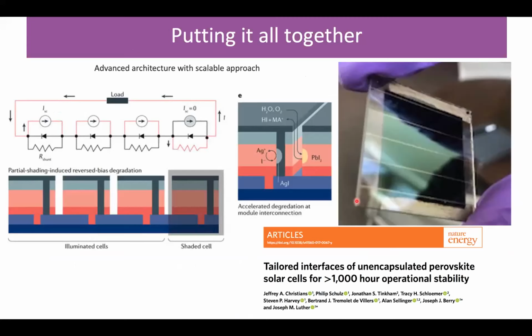Now, when we want to make these things really big, it turns out that one of the things you do is you make cells into mini modules, and you introduce a lot of uncontrolled interfaces from the perspective of this last paper. So that's one of the current projects we're working on, is basically making these kind of devices where we're introducing scribes and subcells and things, but still trying to maintain control over the details of the interface and not allow things like these kind of mechanisms to impact on the solar cell stability.